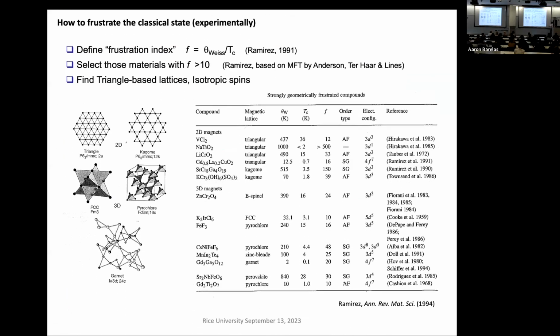And this led to one of the early materials compendia of frustrated materials, and it became clear to me that, yes, just using that criterion of that F ratio, you found that all the systems were based on triangles. These are the different magnetic or mineral classes. These are pictures of the magnetic lattice. And so I defined this frustration index as one way of demarcating classes of materials.